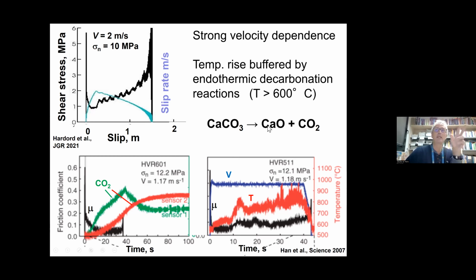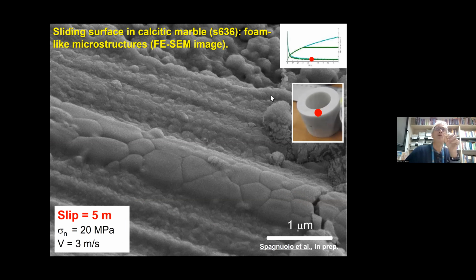And this is where we observe those flashes, very bright flashes. If you stop the experiment after a meter of slip or less, you will find on the slip surface this kind of texture. This is a field emission secondary electron image. The scale is 1 micron, and you can see this sort of pavement. The original grain size was 500 microns. However, these things are 500 times smaller. Okay, they're only 1 micron. So there is something interesting going on.